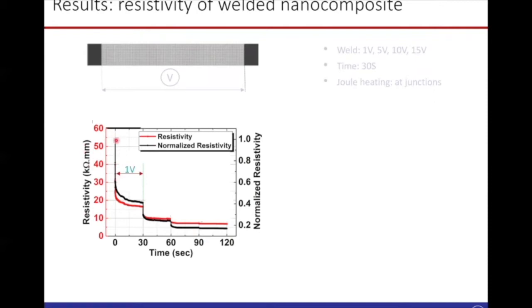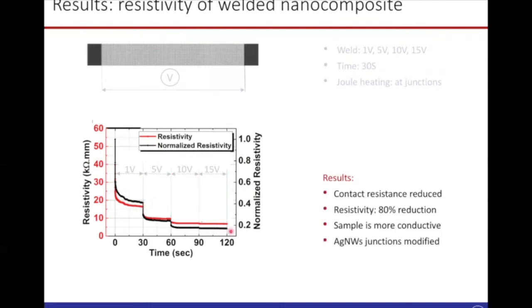And as you apply 1 volt, its resistivity reduced drastically and it's quite saturated. Then we increase the voltage to 5, 10, and 15. And the sample became more conductive at the end. And that is saturated, meaning there is no point in increasing the voltage further. If you increase the voltage, it may burn your silver nanowire, so we stop after 15 volts. At the end of the welding, the resistive sample became more conductive and the resistivity reduced by 80%. This is all because we believe it modified the junction. So it means you can control the contact resistance by welding.